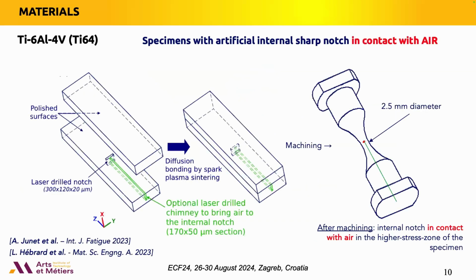And the other set of specimens produced uses the same procedure, but the idea is to allow the air of the lab to come into the crack inside the specimen. So we produce, by laser machining again, a small canal or a small chimney that allows the air molecules to come into the crack, into the center of the specimen. So we use the same procedure, and finally we obtain the specimen with the central defect and the chimney to allow the air to come into the specimen.